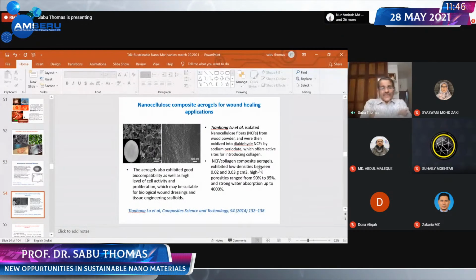Let me show the work of Professor Liu in China. Professor Liu and colleagues made nanocellulose collagen composites. Collagen is a very, very biocompatible natural polymer. And density of the material is 0.02 to 0.03 gram per centimeter cube, very light density. And porosity is 95%. So he combined nanocellulose and collagen and made aerogel. You look at the water absorption capacity of this, it is 4,000%. And Professor Liu said this is an excellent material for wound dressing.